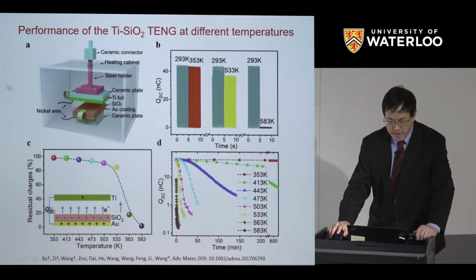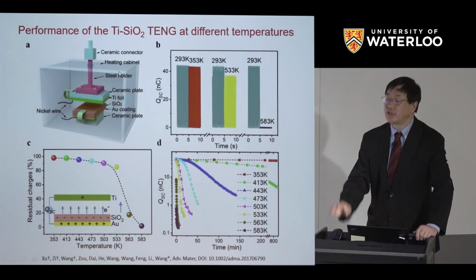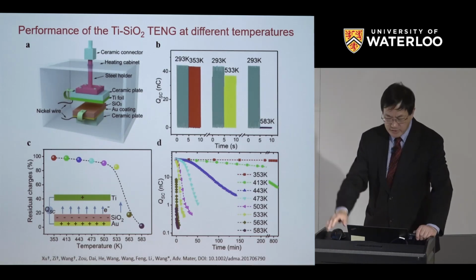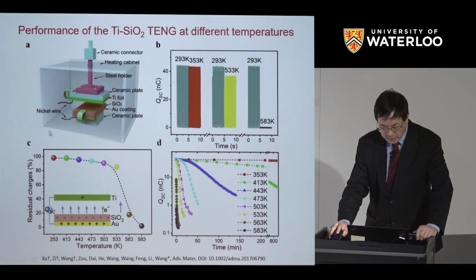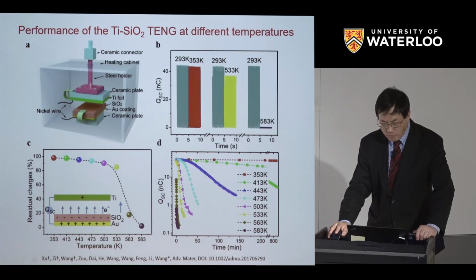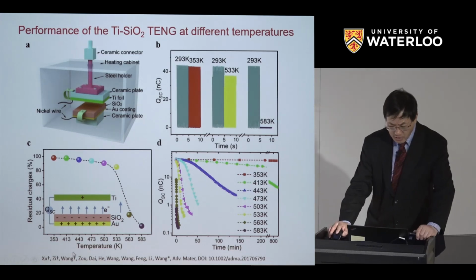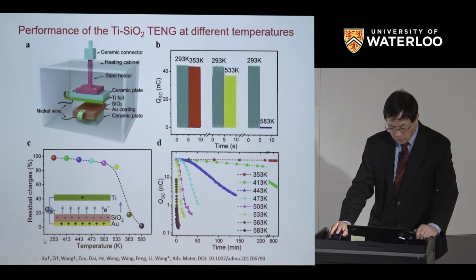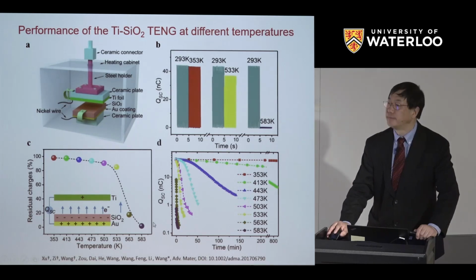Two years ago, we made our triboelectric nanogenerator, as I showed you just a moment ago, that thing's rotating inside a tube, this box tube furnace, so we can control the temperature. So we measure the output of the triboelectric nanogenerator as a function of temperature. What we find, raise the temperature from 293 Kelvin, roughly room temperature, to above 533. So this is about 250 degrees C. You can see the triboelectricity drops dramatically.